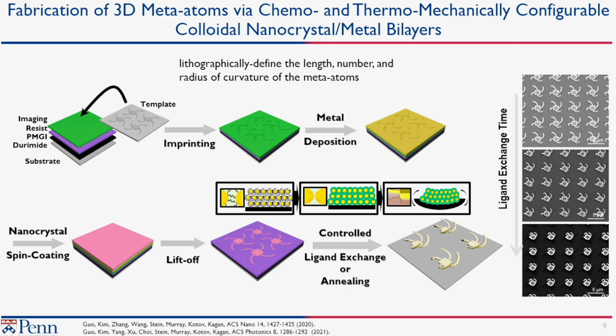We can deposit, for example, a thin layer of material by evaporation, for example, metal. We could spin coat our nanocrystals, and then once they're on the surface, we could do this ligand exchange process that really wants to bring the nanocrystals close together. And so these will then fold. We can also anneal them. If you anneal them, it'll drive sintering of the nanocrystals. It'll create greater strain. It'll create greater folding.